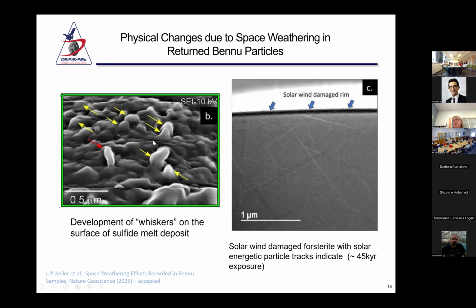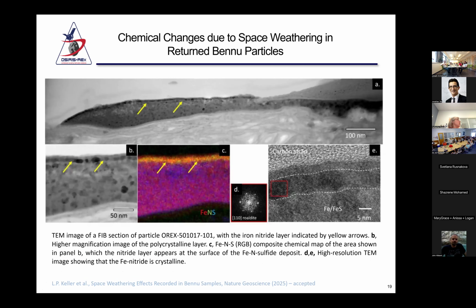We see other evidence for space weathering, including the solar wind damaged rim. The solar wind is typically protons and helium of a particular energy, so the depth at which these ions can penetrate is generally relatively uniform. It creates a sort of rim on the surface of everything. In addition to that, you see these little tracks here. These are from energetic particles from the sun, and determining the density of these tracks can give you some indication of the exposure age of that particular particle. In this case, it was 45,000 years that this had been on the surface of Bennu.